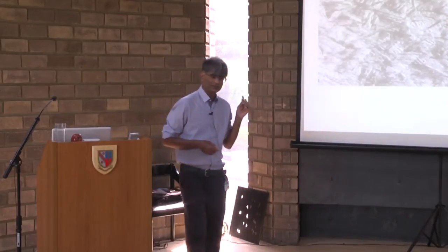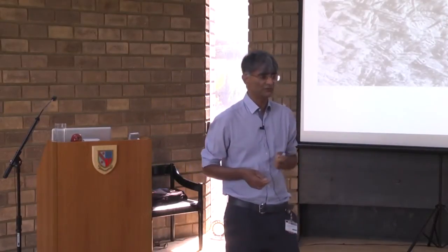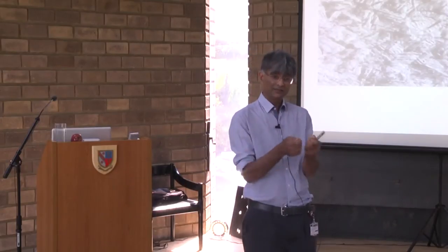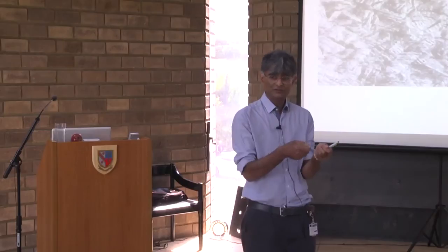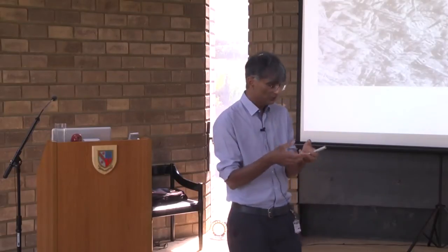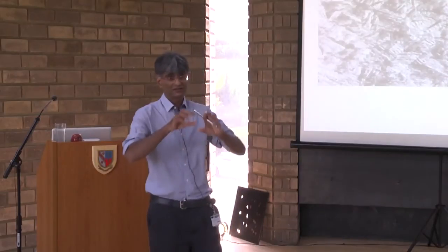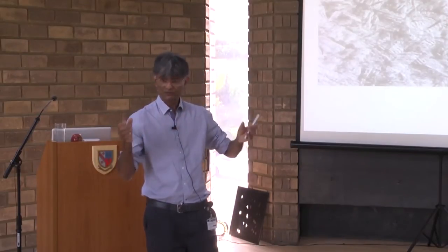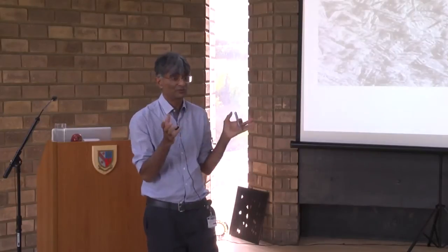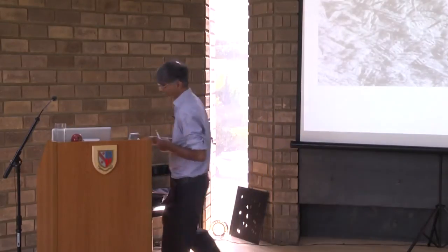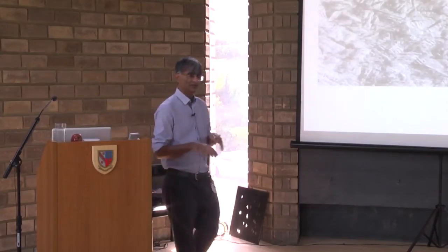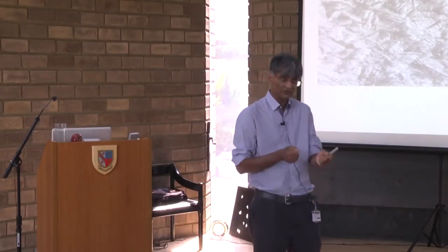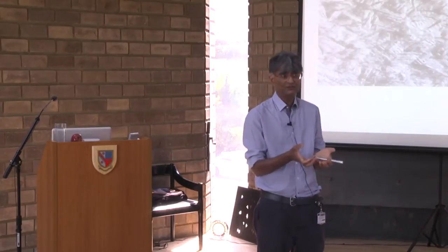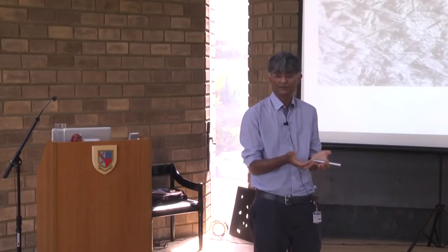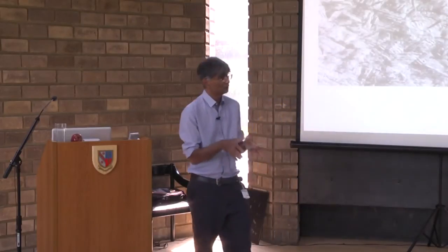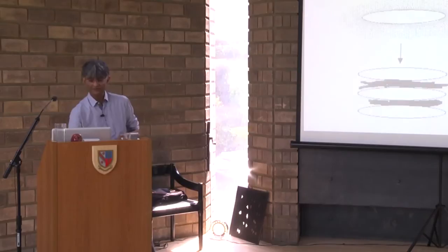Now, these are very large deformations. Okay, so there's a shear strain of about 0.26. That compares with a typical elastic strain, which is 0.001. So in order to minimize the strain energy, the crystals form as thin plates, which is very good because we want them to be as thin as possible. That's a fine crystal. And the elastic strain energy, this is happening inside the bulk of material, so these crystals are pushing against each other, effectively reduces the heat that is released when the transformation happens. Okay? So you're storing the energy inside the material rather than releasing it as heat.